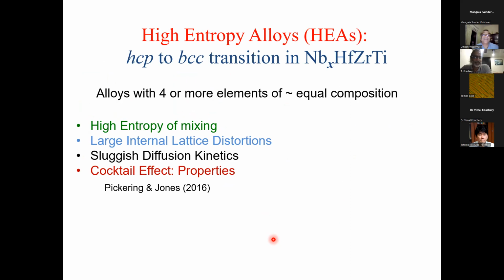Yeah, so these are again a relatively new type of materials called high entropy alloys. And these are alloys where you have more than 4 elements of equal composition. And what is believed is that in this condition, you have very high entropy of mixing, which stabilizes these alloys. This is in contrast to traditional alloying, where you start with, say, aluminum and put a little bit of another element. Here it's like you have 4 different or 5 different elements with roughly the same concentration. And because the chemistry of each atom can be different, size can be different, they lead to large internal lattice distortions, and of course involves sluggish diffusion kinetics, which stabilizes their single phase structure.